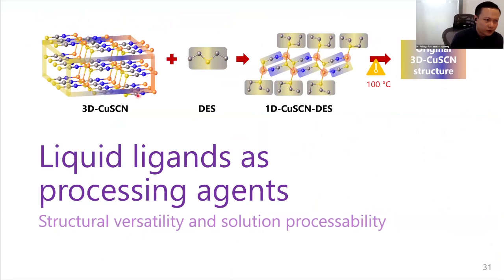So CuSCN, as a three-dimensional structure, is processed with the diethyl sulfide, and this can actually result in an intermediate structure - it can be many structures that I'll talk about later. Then we can remove this and obtain back the original three-dimensional structure. In this intermediate structure, we can see that there are two ligands together: the primary ligand here is copper with SCN, the thiocyanate ligand, and the secondary ligand, which is more weakly interacting with the copper, is diethyl sulfide.